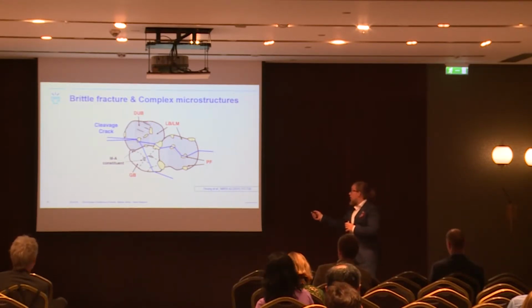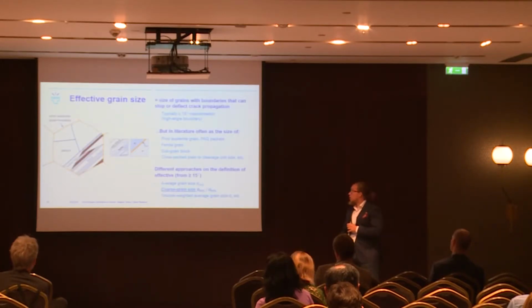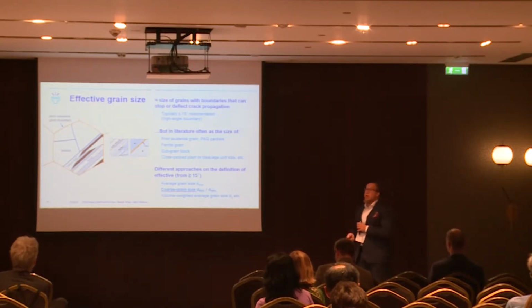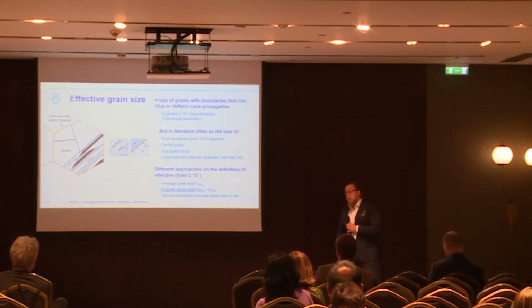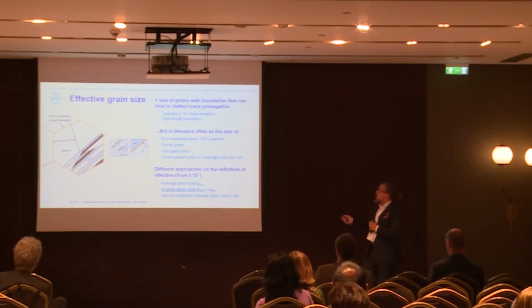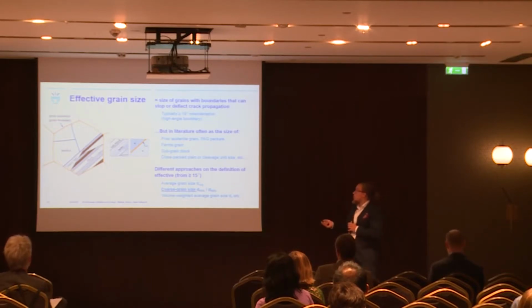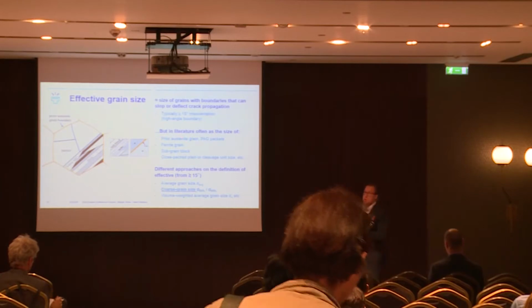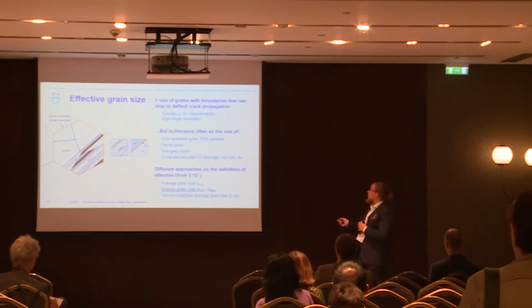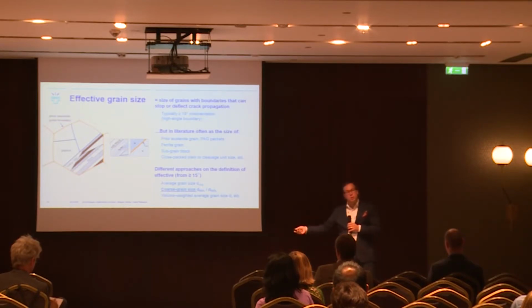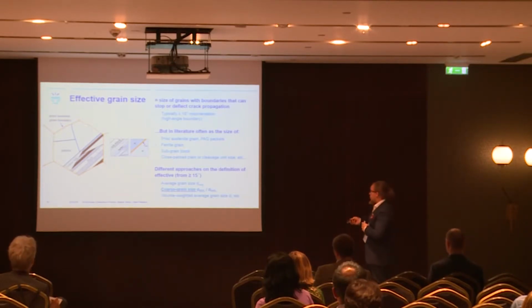To get from this to sample level properties, we use the effective grain size, which simply is the size of the grains with boundaries that can arrest the crack. That is usually grain boundaries with a misorientation of at least 15 degrees. That is well known, but in the literature it is often referred to as the size of prior austenite grains, ferrite grains, subgrain blocks, but also packets and cleavage unit sizes and so on. Partly for historic reasons, but also recently there are many studies showing that different features are to blame.